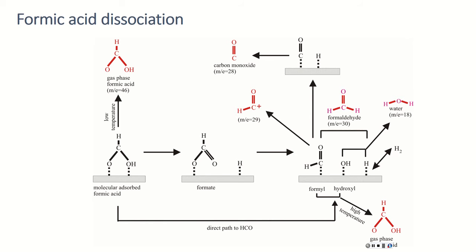Right, yeah. But it depends on the temperature; here we have the activation energy. When you have submonolayer coverage, we needed about 600 Kelvin for the decomposition, and up to that temperature it was stable in vacuum. That means we don't have a huge hydrogen source, but still, without that hydrogen source it was possible to desorb it.